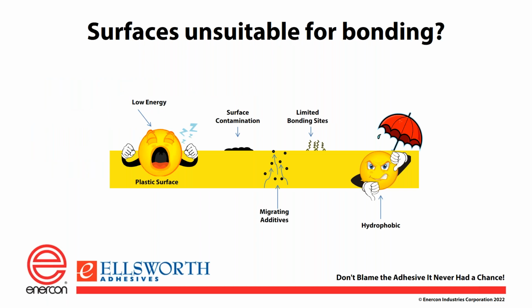So what we're looking at here is just a graphical representation of a low surface energy, a hydrophobic surface. Water phobic means fear, so it's repelling the water on the surface, or in this case, it may be an adhesive. Again, you might have a low surface energy, plastics in general, or low surface energy materials. That means they have limited bonding sites. There might be contamination, and then there are the additives that you see there that might be migrating to the surface and causing a problem with that surface and making it harder to bond to.